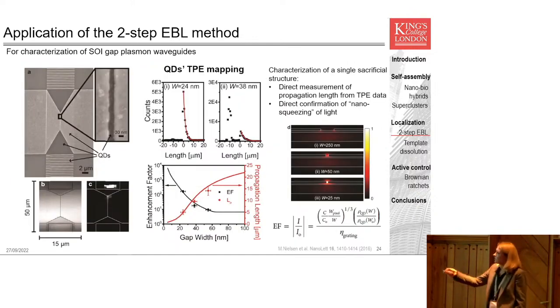And indeed, this is what we did. So here you can see these little blobs, which are quantum dots deposited in the waveguide. And this is a CCD image of our waveguide when we coupled the light. So this is the coupling grating. You can see some reflection from it. And then this is our waveguide, and you can just about resolve the two-photon emission signal coming from the waveguide. So we can then take a cut across this gap and plot it as a function of length. And then the propagation length we then obtain from a very direct fit to the two-photon emission data.